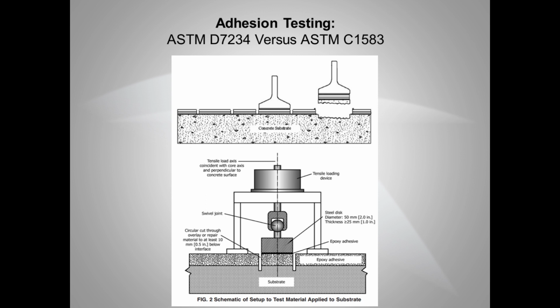There are a lot of different standards to be considered. But if you look at this particular picture on the top, that's an actual picture out of ASTM D7234. When we're done installing our epoxy and our mortar, it should be bonded to the concrete or brick substrate tightly enough that if we pull off a dolly like you see in the illustration at the top, it should actually pull the epoxy, the mortar, and probably some or quite a bit of the underlying substrate.